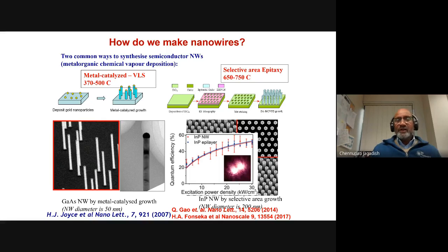So then we went off and looked at the light emission from these structures, and we excited these nanowires with a laser pulse to generate electron hole pairs, and looked at the light coming out of those, so-called photoluminescence. And you can see that the quantum efficiency of the light emission from these indium phosphide nanowires, the red curve, is very much comparable to indium phosphide epitaxial layers, indicating that the surface recombination does not play an important role in the case of indium phosphide, and also that we're able to get excellent quality indium phosphide nanowires, enabling us to get excellent quality efficient solar cells, as nanowires in this particular case. These are very good for making lasers and solar cells and a range of things, for example.